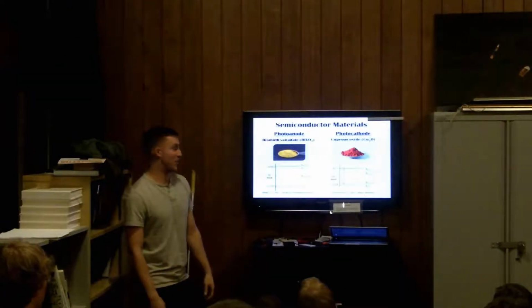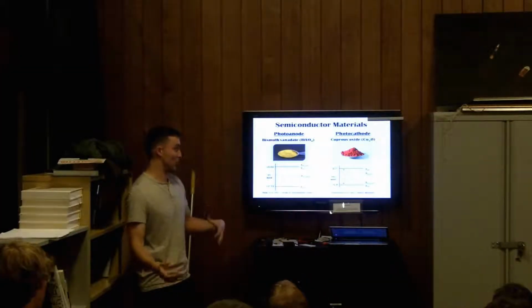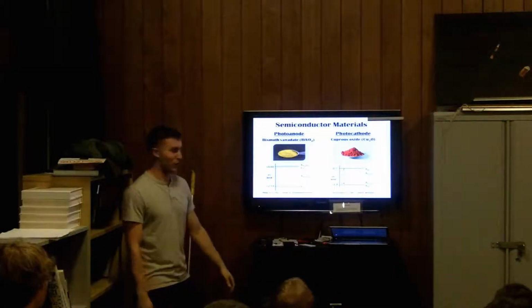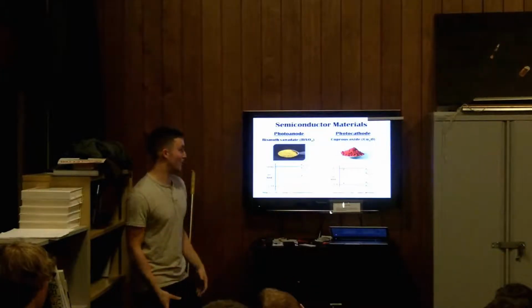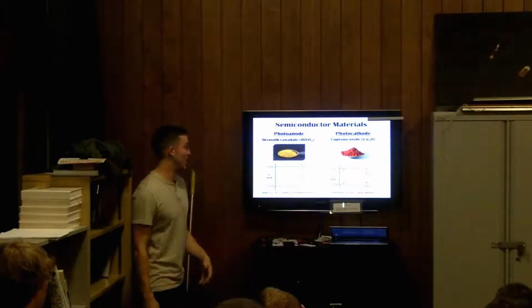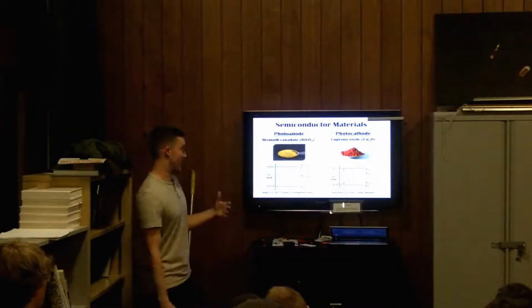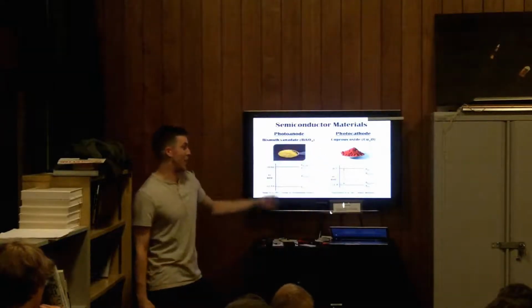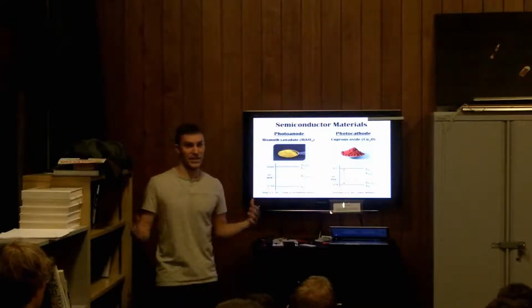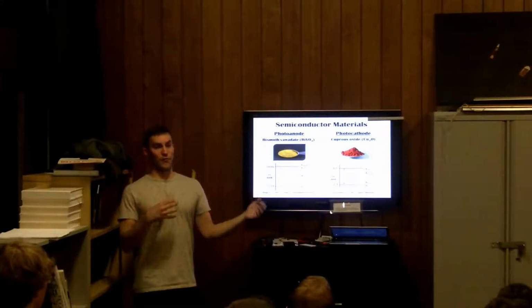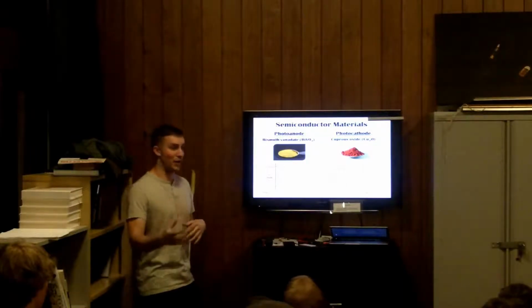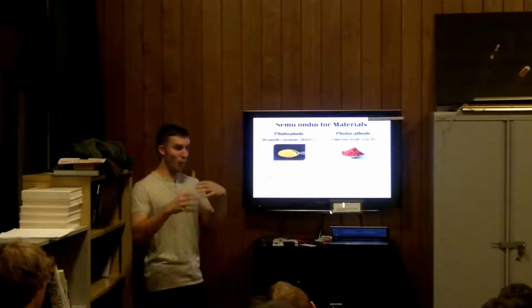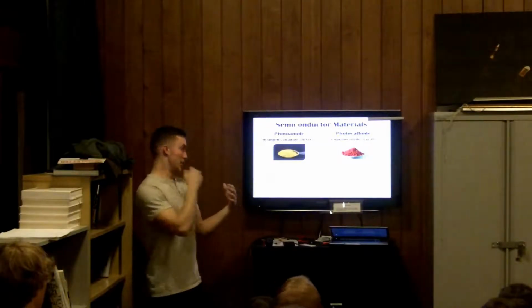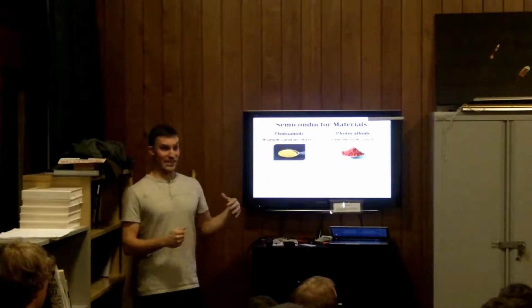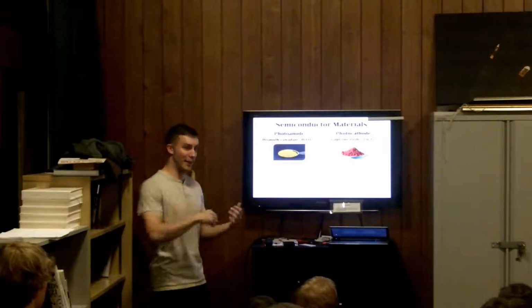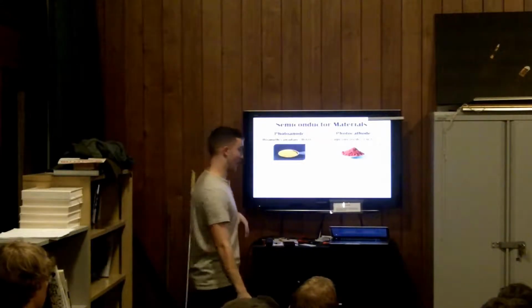Photocathode material that's receiving a lot of study these days is called cuprous oxide, another well-colored compound, which means that it's photoactive again, so that's always a good sign. And you can see that the band gap there is slightly smaller for cuprous oxide, meaning that it can absorb more of the solar spectrum. It can make better use of the light that's hitting it because more of the photons will have enough energy to excite an electron from the valence band to the conduction band and then flow through the circuit and do meaningful work.